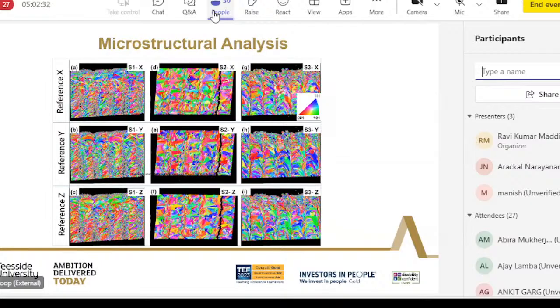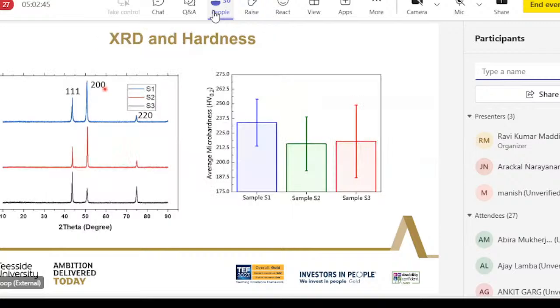I've not put much of the analysis in this particular slide, but the whole work shows that the energy density plays an important role in controlling the grain size of the samples. The XRD data shows that the phases are similar, but if you go to the hardness values, you can see again the lower energy density samples have a higher hardness value, while other samples have a lower hardness value.